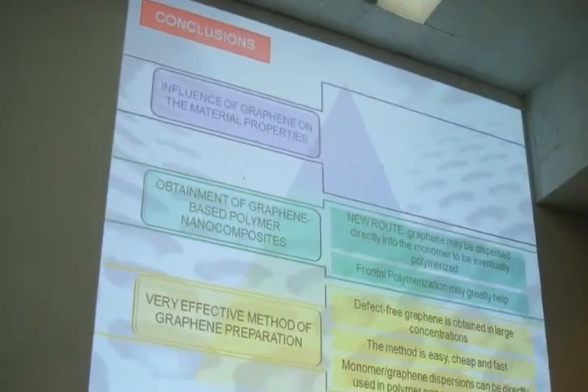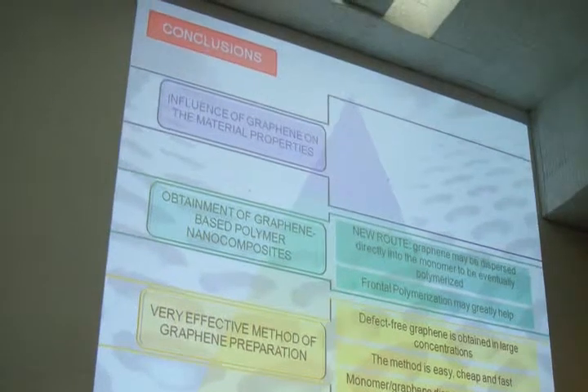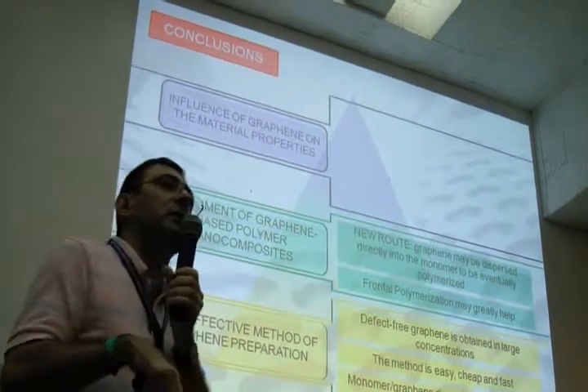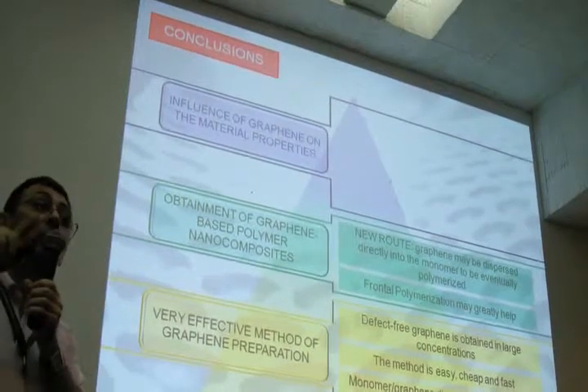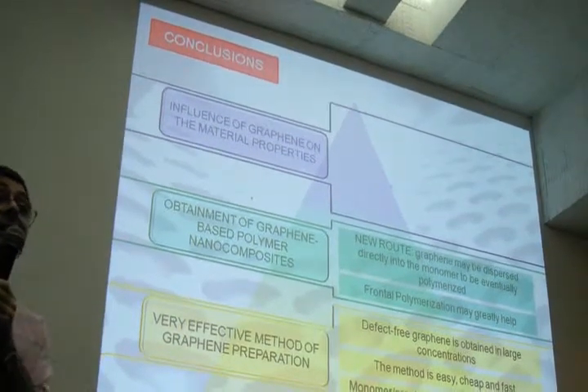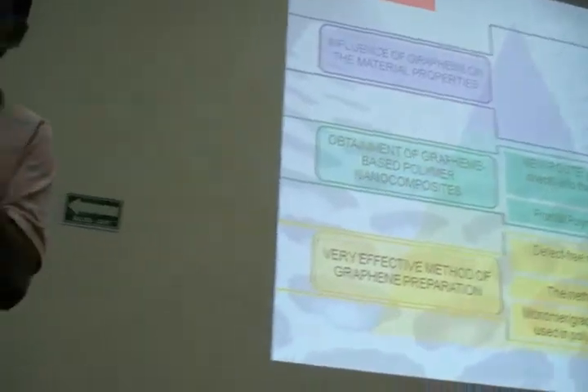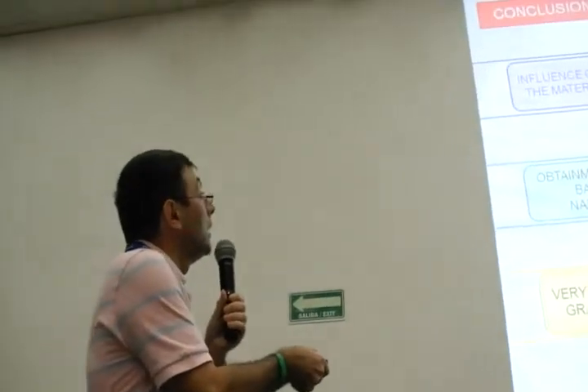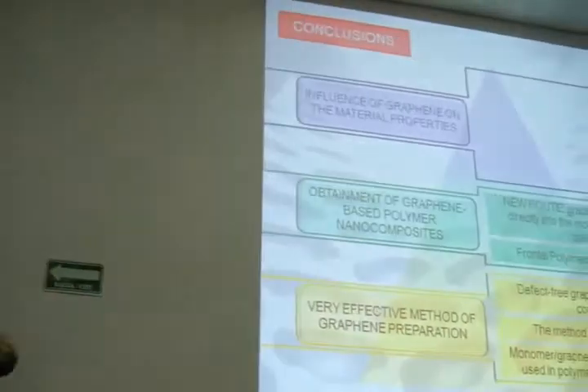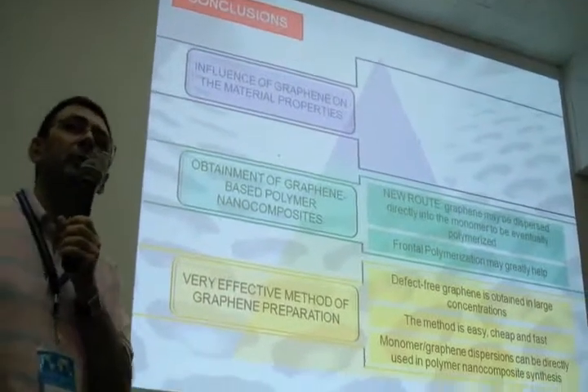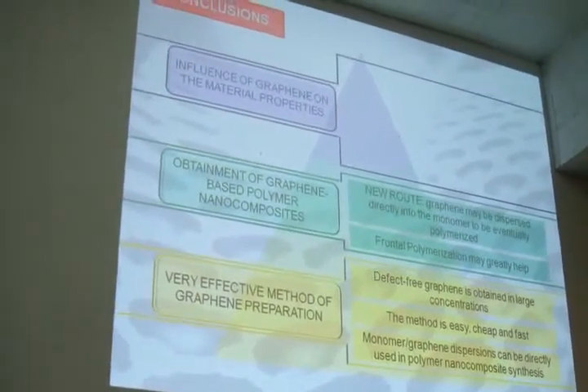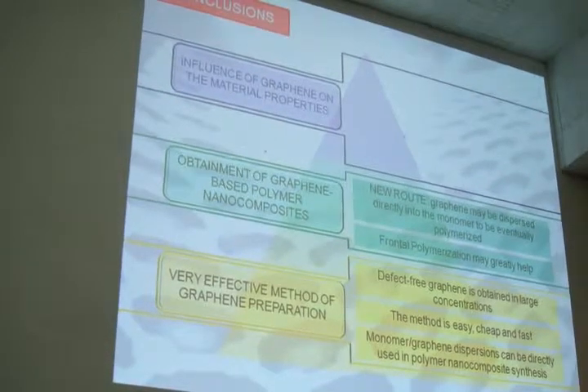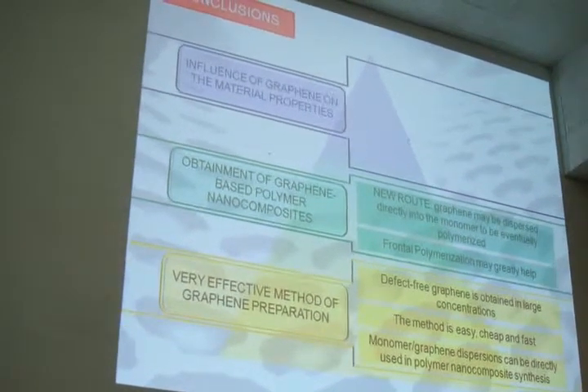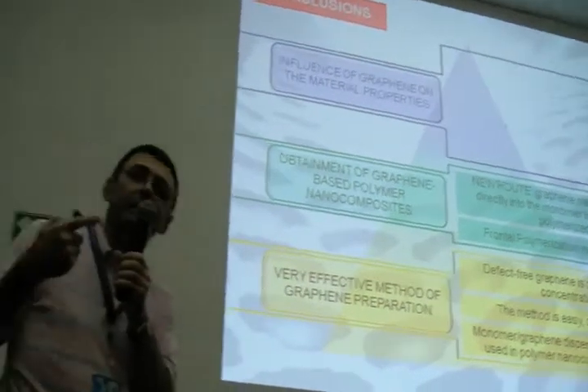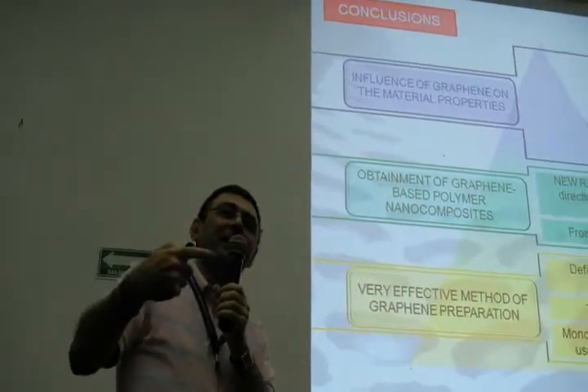It's also important that you can use a monomer directly for dispersing your graphene, and so you can polymerize it directly without any recovery of this nanofiller, so you obtain directly the nanocomposite. In some cases, during the polymerization process, you can have reaggregation, and so the suggestion is to use a fast polymerization technique. Frontal polymerization is one of them, and it's easy and cheap too.